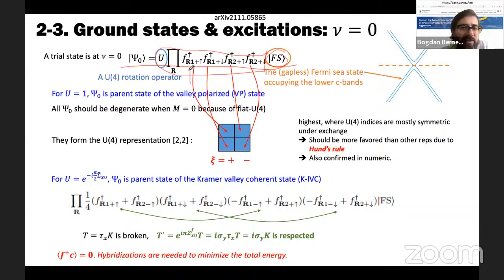And the way you fill up these f-electrons, there's many, right? There's valley, spin index, etc., which is actually given by Hund's rule on the U4 spin of these f-electrons. And there are many rotations, and these rotations of the f-electrons have different names in the literature: Kramer valley coherent state, valley polarized, intervalley coherent states, etc. So these are just some U4 rotations of this. And when this parameter m was 0, all these multiplets are exact. They should have the same energy. And when it's not 0, they don't have the same energy. Before, there was no nice way of understanding which one would be lower. But now, by just simple rules, there is a way of understanding which one's lower.